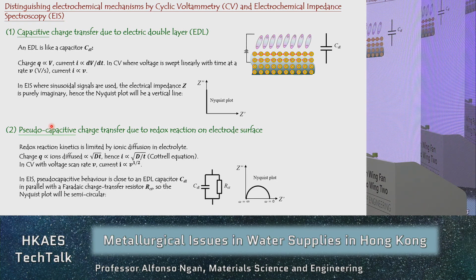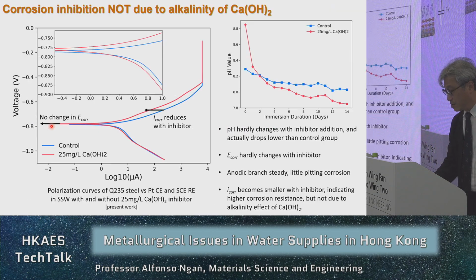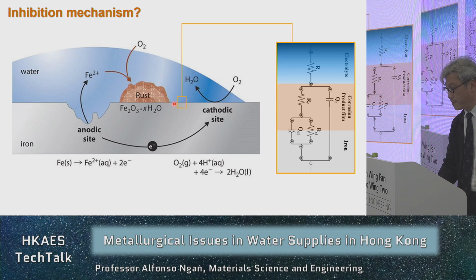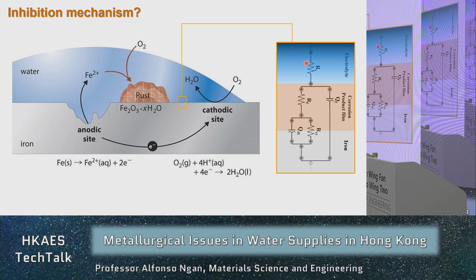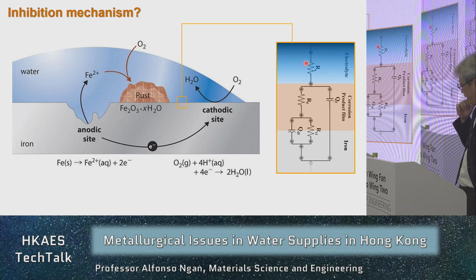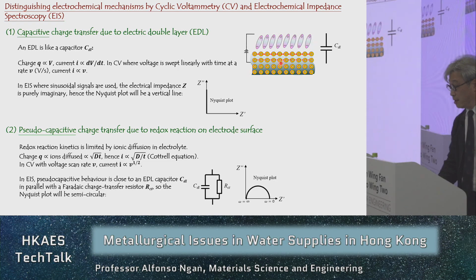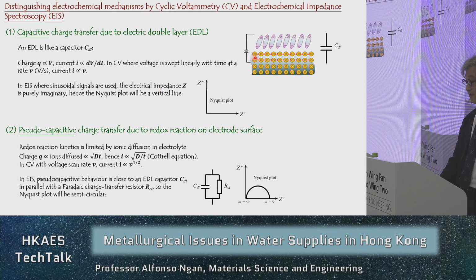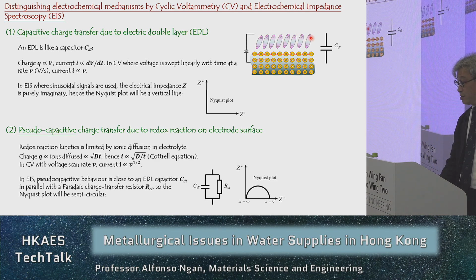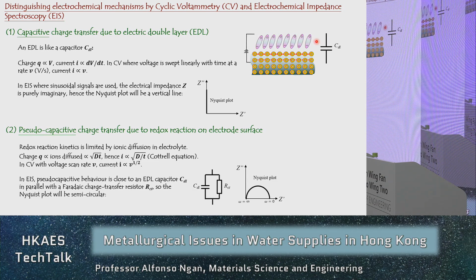So we had to dig deeper then in order to find out what is the mechanism. So just to go back to that interface that I was talking about, the metallic and electrolyte interface, this one, right? As I said, people usually use this sort of equivalent electric circuit to model the charge transfer across that interface. So what could the resistor or what could the capacitors represent? Basically, in the atomic picture, the capacitance or capacitor arises from the electric double layer. All right, so if you have a clean metallic surface and if you charge the metallic surface with respect to the electrolyte, you would encourage the generation of a layer of double charges. That is what people call EDL, electric double layer, in the electrolyte. So once you have this dipole layer, it looks like a capacitor. It behaves as a capacitor, all right?